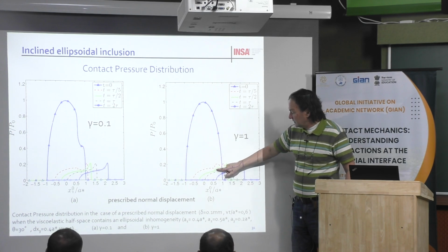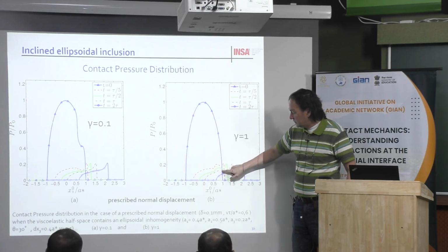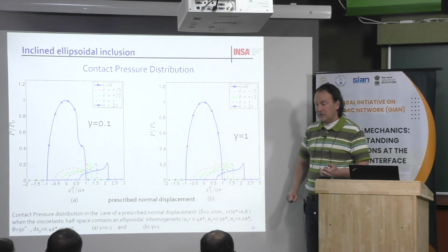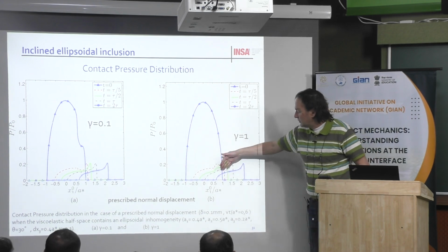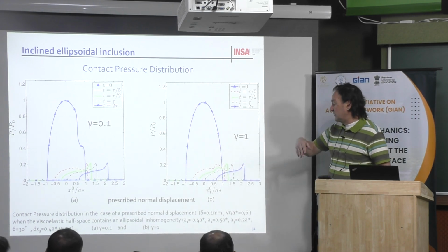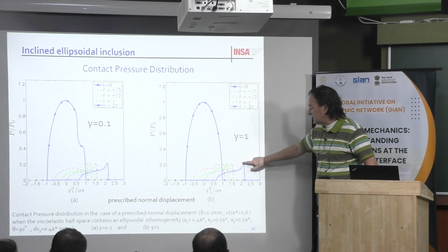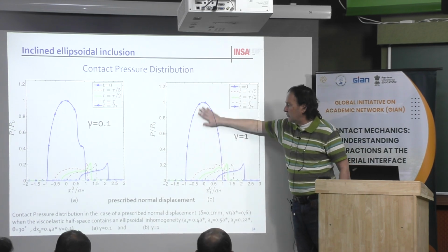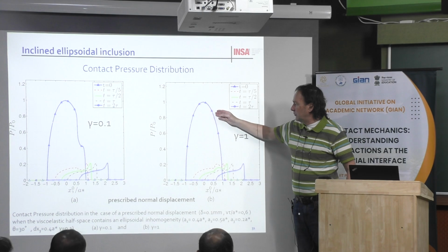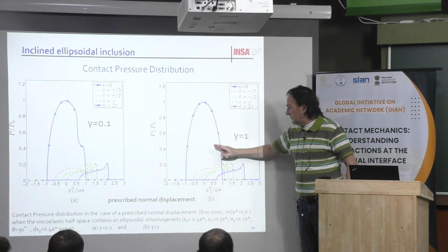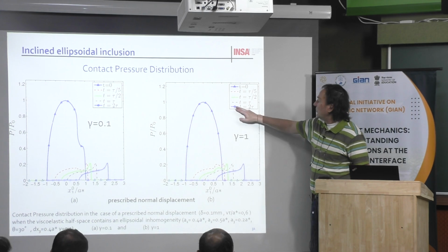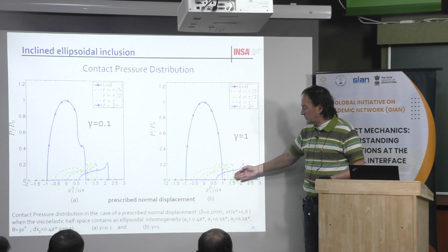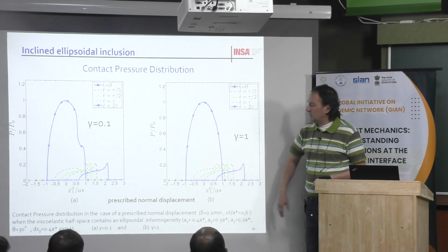Then you have something with one peak due to the presence of the inclusion, and the other peak due to the viscoelastic behavior of the matrix. And after a while, because you have left the inclusion behind you, you have only the steady state solution. Then if you integrate not the area but the volume below the pressure distribution, you can see that for this situation and this one after a given time, it is not the same. This is why the load is much smaller in this situation.